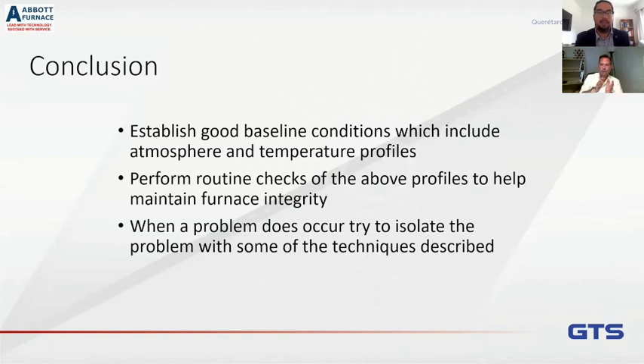Yep. So basically, if you go away with anything, I want you to go away understanding that you need to establish good baseline conditions, which include a good temperature profile and a good atmosphere profile of your process when you're making good parts. If you then perform routine checks, at least once a year you do an atmosphere profile, and once every 6 months you do a temperature profile, that will allow you to hopefully schedule downtime and not be surprised by it. So you have control of your destiny. And then when a problem does occur, do the temperature profile and do the atmosphere checks to isolate the problem, and then use some of the tools that we gave you to try and locate the problem and address it.